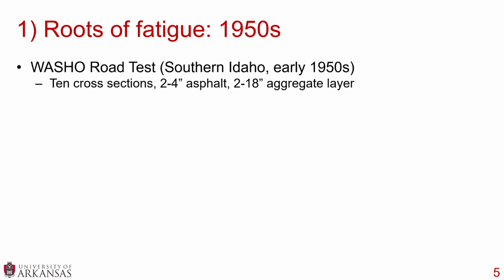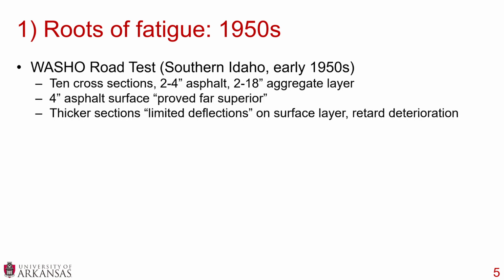In the roots of fatigue, the Washoe road test took place in southern Idaho in the early 1950s. It involved 10 different cross sections, anywhere from 2 to 4 inches of asphalt and 2 to 18 inches of aggregate layers. They found that the 4-inch asphalt surface provided a far superior product, and the thicker sections limited deflections on the surface layer and retarded deterioration. So let's keep that third bullet in mind about thicker sections retarding deterioration.